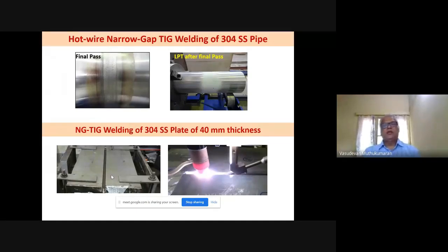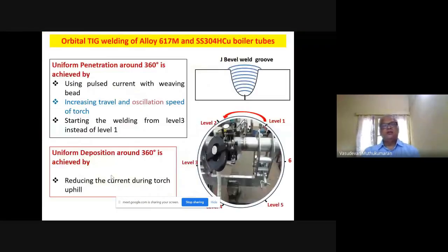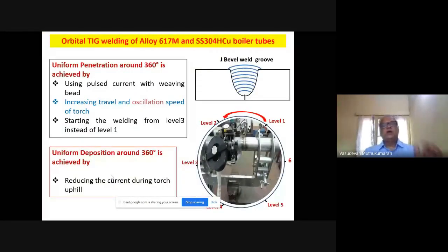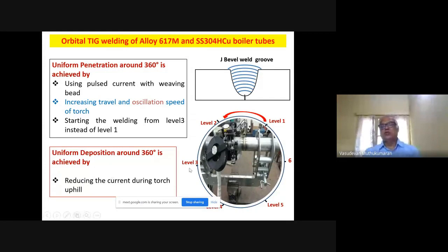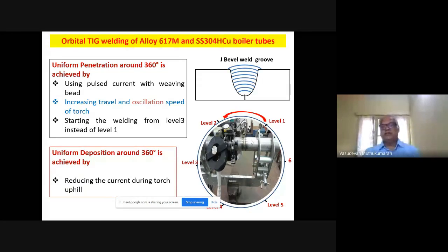Coming to orbital TIG welding, here we are using this process mainly for AUSC components like 617M and 304H copper boiler tubes. And we are using pulse current because there are different quadrants, the torch moves through 360 degrees. We are varying the current from quadrant to quadrant. We adjust the current to get the full penetration and defect-free joint.